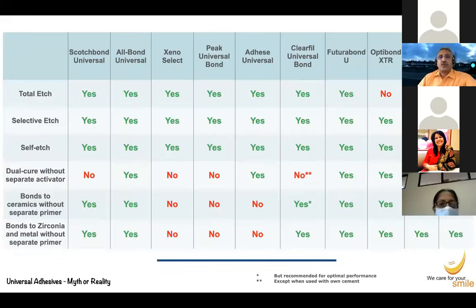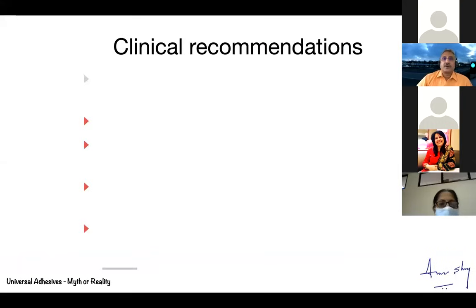Okay. So now if we come back to this chart, which I had shown you earlier, if you look at this in toto now, what you will find is there are some, like say All-Bond Universal, which do everything. There are some like Scotchbond Universal, which does everything, but it needs a dual cure activator if it has to be used with another company's cement. Remember, I gave you the example of using 3M bonding with GC cement, whereas some you cannot use without separate primer and you cannot use without dual cure activator at all. So there is a lot of difference between different companies and different products, and you need to actually look at the details of whichever product you choose to go in for.